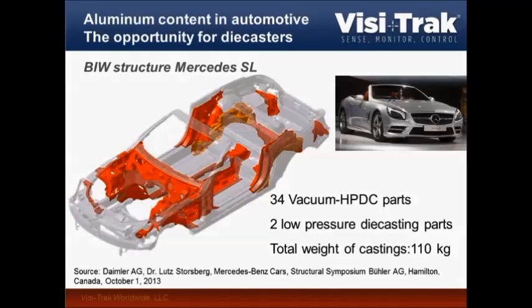Now if you look at the castings, as I said, the majority is structural die castings. We have 34 high vacuum, high pressure die casting parts here in red, and in orange you can see 2 low pressure die cast parts. Those are very big and very complicated with internal cores. The total weight of the castings is 110 kilos, and interestingly enough, the weight saving over a traditional steel car body with this aluminum body was also about 110 kilos.